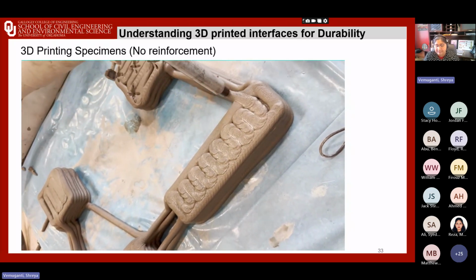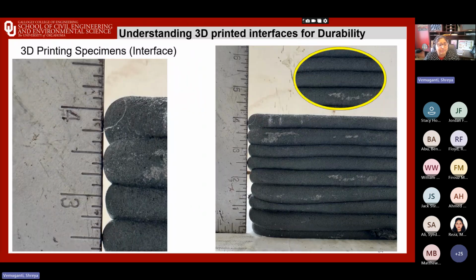Please also notice in the next slide these visible interfaces. This is after the hardening process. You see a close-up of the 3D printed specimen. Each of these ridges represents a layer-to-layer interface, right? And this doesn't look like the way cast concrete looks, right? That material is monolithic. The 3D printed elements, however, are fundamentally a layer-on-layer build-up.